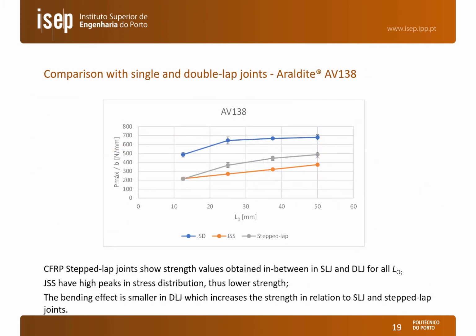By comparing with single and double lap joints, and here we just present an example for the Araldite AV138, we can see that the results of the step lap joints are in between the single lap joints and the double lap joints, and this is because the behavior of the step lap joints is improved with respect to the single lap joint, which is presented in orange. This is because we are having smaller stress concentrations and smaller eccentricities in the load than we have in single lap joints.